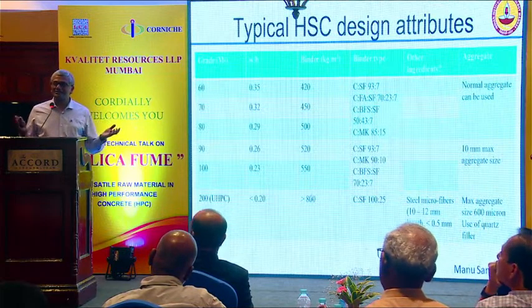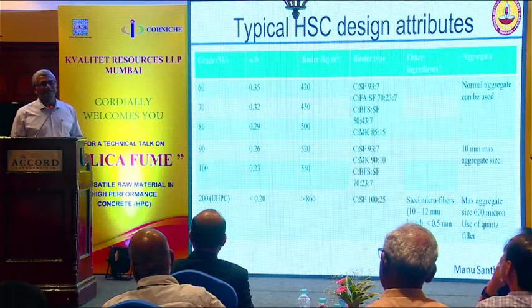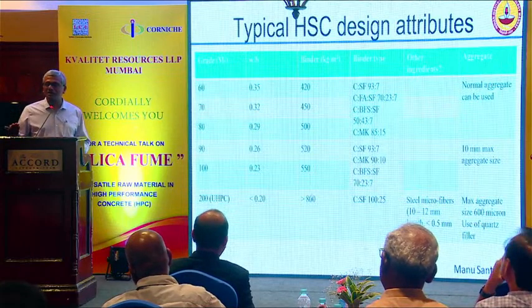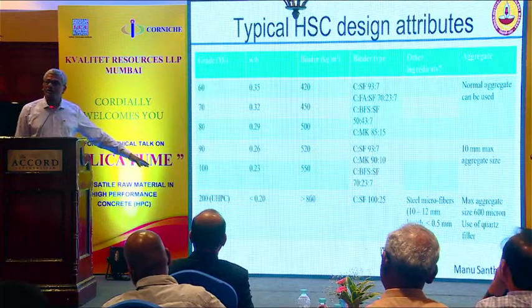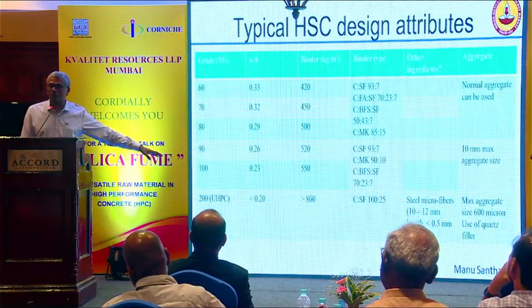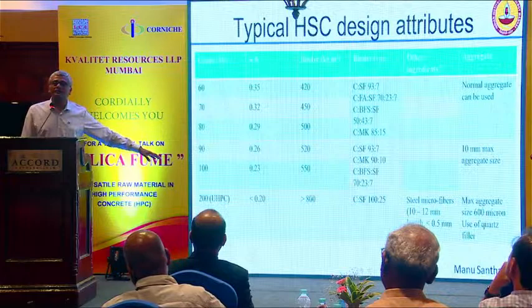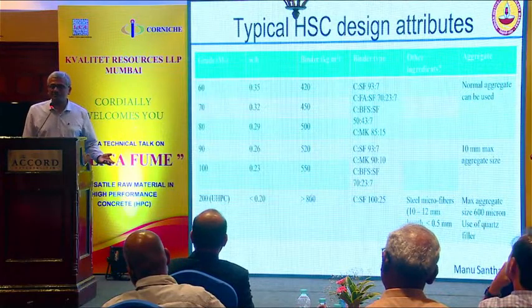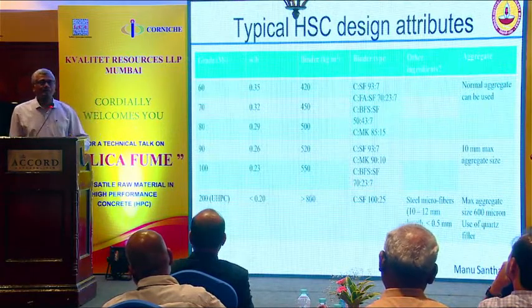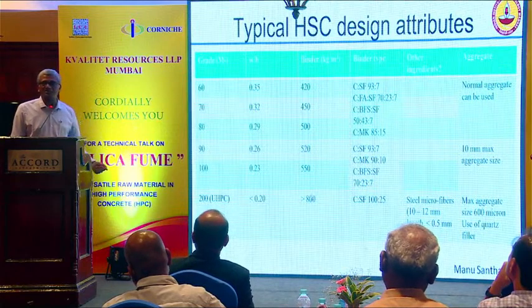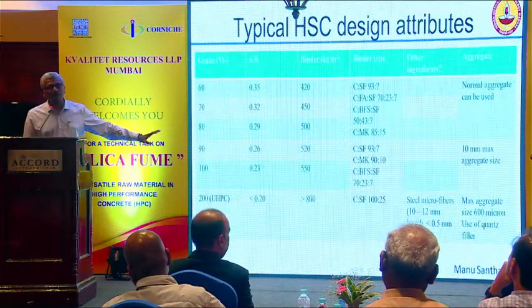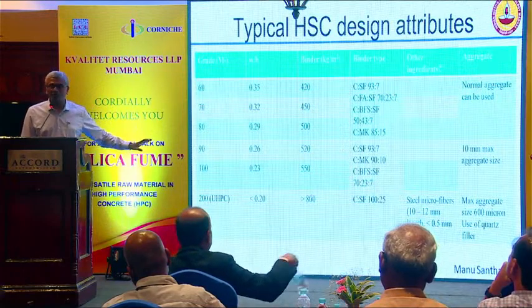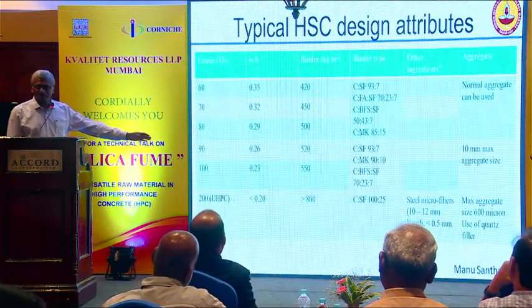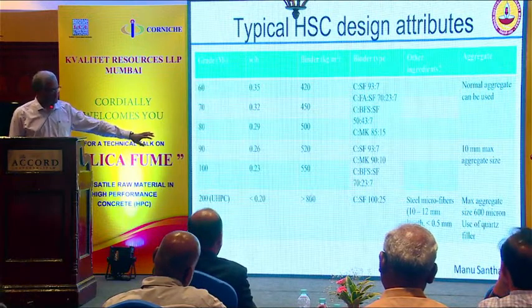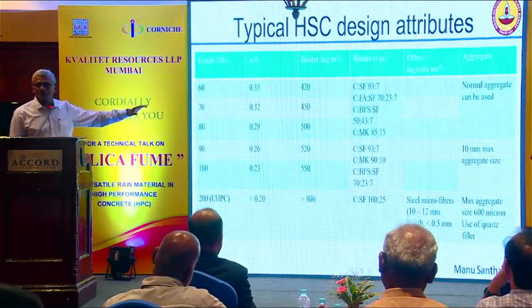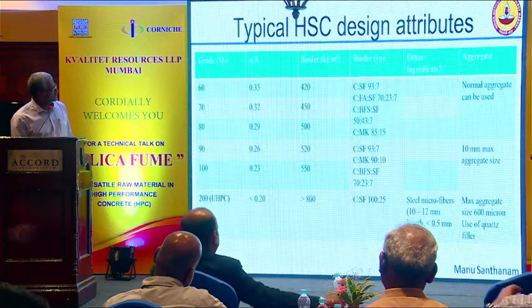Of course, all this is nice to do in the lab. In the real field, that level of strength may not really play a role. But 200 megapascal UHPC is playing a role today. People are trying to look at replacement of steel in some sections. I'm talking about structural steel in compression members, where you can easily do with UHPC. It can provide you sufficiently good flexural resistance also to provide a good performance. Okay? So again, here steel fibers are typically used, short steel fibers, but silica fume is an integral component of most of these high-grade concretes.